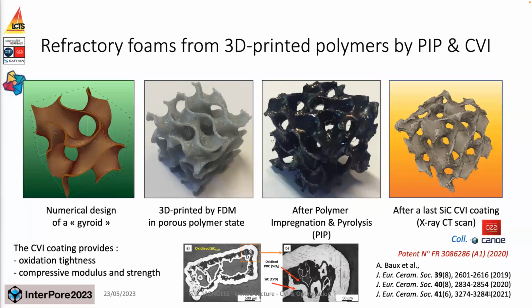Just to give you an example of a recent production from my lab, we went from the numerical design of a gyroid-like structure that has been first 3D printed by fusion deposition modeling in a porous polymer state. Right after, it's been impregnated with a pre-ceramic polymer and pyrolyzed. And the last step was to add a chemical vapor infiltration coating. And as you can see in the slice at the bottom, the CVI coating gives a very good oxidation tightness to the ceramic, and also increases a lot the compressive modulus and strength of this ceramic foam. So it's been even patented.